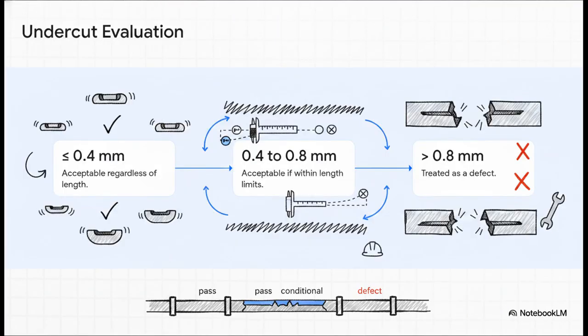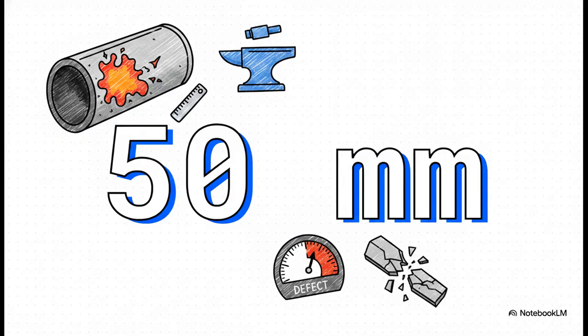Well, the specifications give us a crystal-clear triage process for issues like undercuts. Shallow cuts under 0.4 millimeters, okay, those automatically pass. But hit that mid-range between 0.4 and 0.8 millimeters, and inspectors have to start carefully measuring individual lengths against some really strict ratios. And anything beyond those limits, it's no longer just an imperfection, it is an absolute defect, and it requires immediate rejection. Another absolute limit you've got to memorize is 50 millimeters.